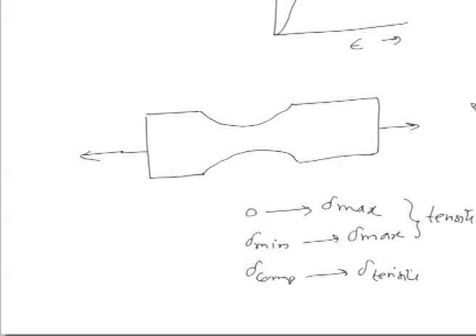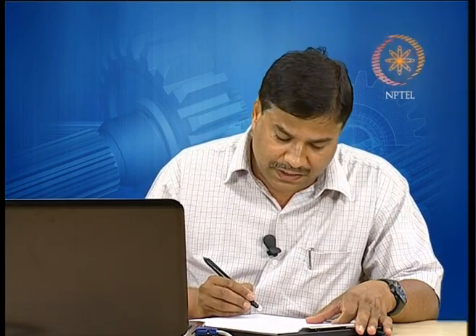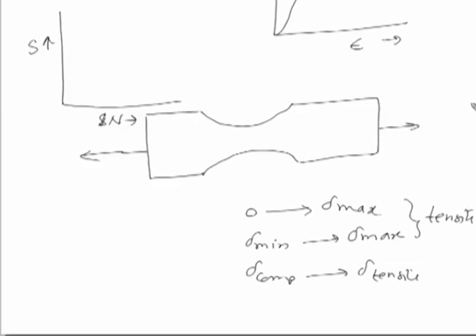As far as the development of the S-N curve is concerned, we need to plot the relationship between the number of load cycles that a specimen can withstand and either the maximum stress or the stress amplitude. It is common to use S for the stress amplitude, which is half of the stress range. We will start with a maximum stress of 0.9 times the yield stress. So, starting with 0.9 times the yield stress as the maximum stress will be taken as the first test. It will use very few load cycles.